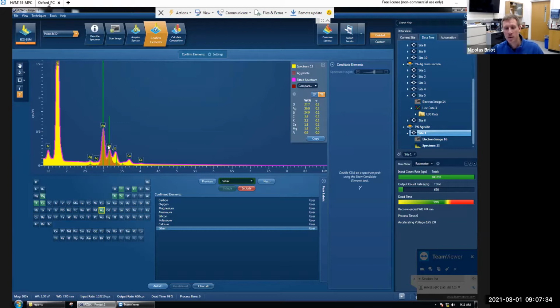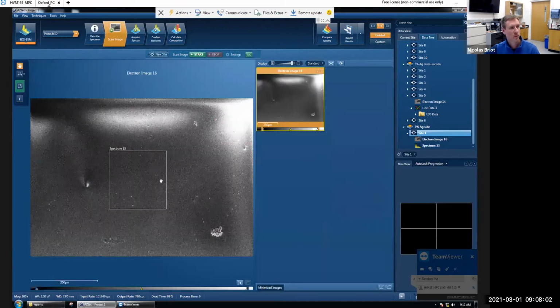I'm not sure. We couldn't see it on those line scans in the physical cross-section when we were grinding the sample. So that kind of indicates to me that it's only the first, maybe 10 microns or even shallower that has silver in it, and maybe that was damaged in the physical process of cutting and grinding. So what I did after the class was that same sample, this one, I did what we were starting to talk about at the end of the class: I did a FIB cross-section.